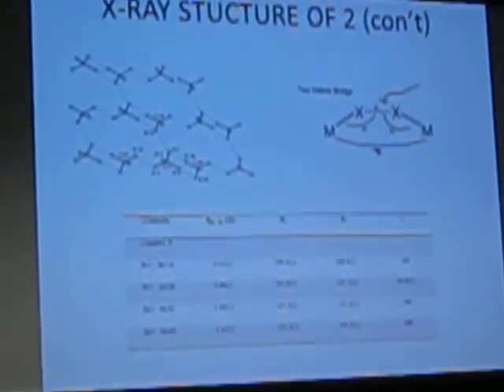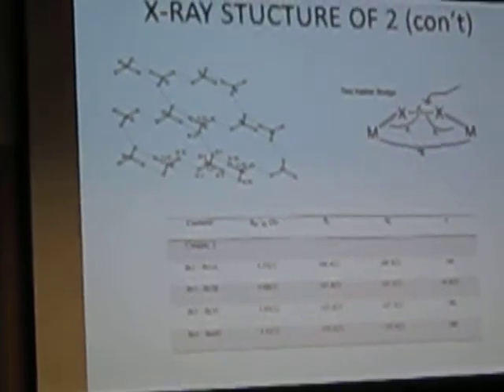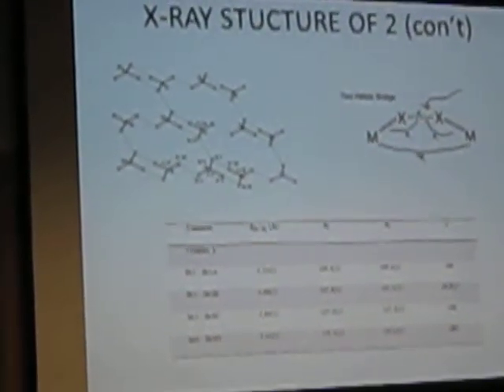So when we look at the stacking of the anions, what do we see? We see a really exciting structure, actually. We see a honeycomb, and it's not a uniform honeycomb, it's a distorted honeycomb. So you can see the 6 points of the hexagon here, so 1, 2, 3, 4, 5, 6. But again, it's distorted. You get only 2 halide bridges in this compound. And we've got reasonable distances to expect moderate exchange across the metal centers here.